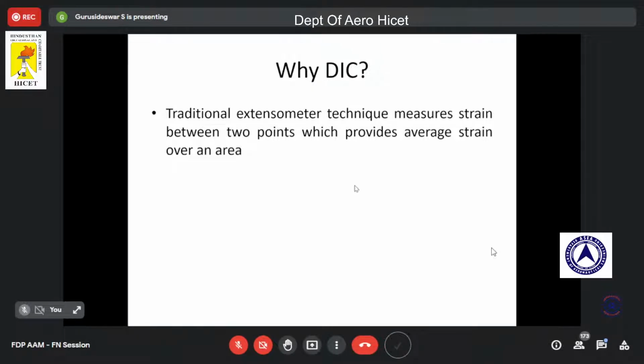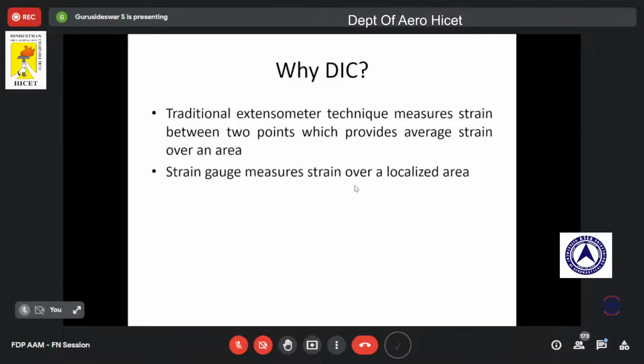In general, we use an extensometer to get the strain data. We have used it in our laboratory, and using the extensometer we get the strain data. But it gives strain between 2 points, based on the gauge length of the extensometer. We also use the strain gauge to get the strain data. We bond the strain gauge on the sample and apply a load, and using a Wheatstone circuit we get the strain data. But the strain gauge gives strain over a small area only.